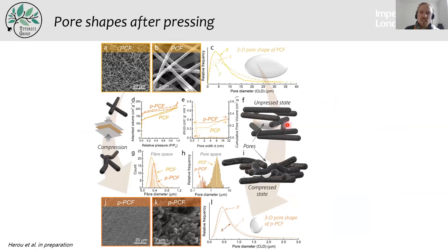And we've also investigated the shape of the pores by X-ray tomography. And we can see that in the unpressed state, all these fibers are stuck on the top of each other. And in the pressed state, they start kind of rolling around and decreasing the pore size from approximately 5 micron to 0.5 micron. And that was quite interesting.